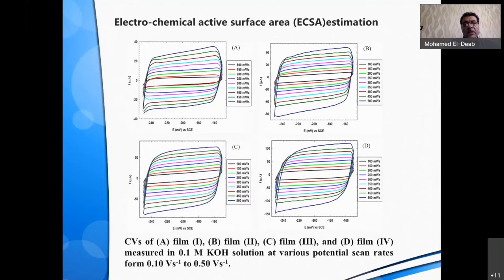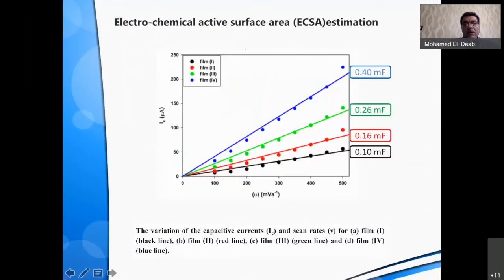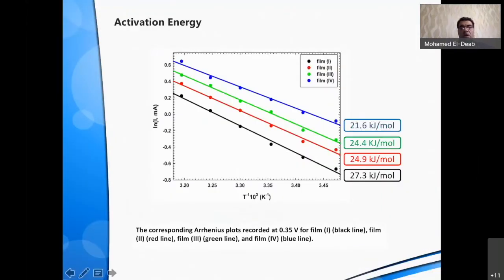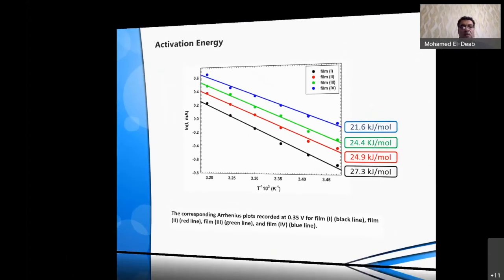We tried to estimate the electrochemical active surface area by measuring CV under different scan rates, and we can estimate that the highest surface area and the highest Faradaic capacity value is for film number 4, which is in line with the observed electrocatalytic activity, meaning that this film has a higher adsorptivity for the spectator ions, so that it allows for higher oxidation current for glycerol electrooxidation. The effect of temperature here also, we estimated the activation energy, and we found that also film number 4 has the lowest activation energy for the glycerol electrooxidation in alkaline medium.